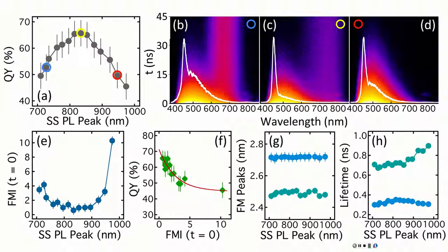Yep. In bulk it should be optically forbidden because of momentum conservation. But in your case, if you jump from the X to the K point, it's a substantial change of momentum that needs to be taken by someone. Don't forget about that.